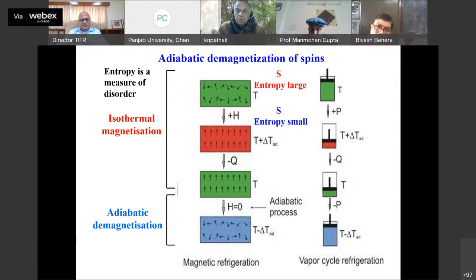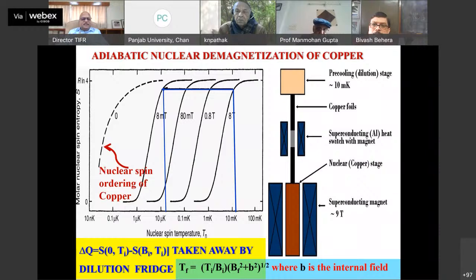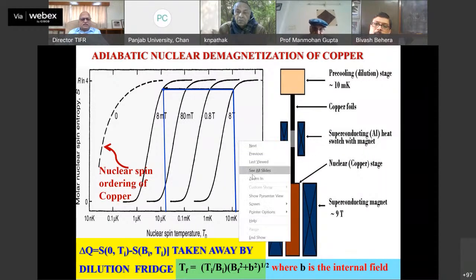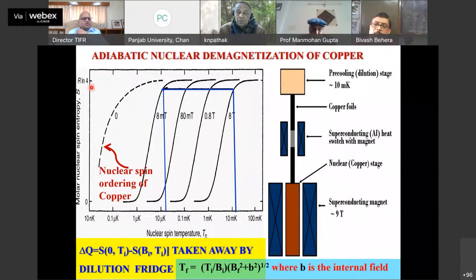Typically, people have achieved of the order of 1 microkelvin with platinum, 10 microkelvin, 50 microkelvin with copper nuclei. So how does one do that? So you can see what you have is an entropy as a function of nuclear spin temperature. So you start at 10 millikelvin and at 8 Tesla, apply the field and then you cool the system with the dilution fridge, then do a demagnetization. Stop at 8 millitesla, you will reach something close to 10 microkelvin. So how do you do this practically?